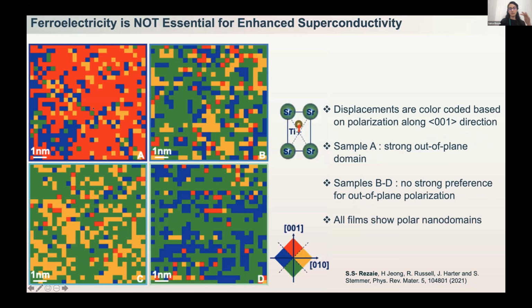Okay, these are the 4 films that we have looked at here. Film A, which I showed you earlier, had that strong transition to the ferroelectric state, and you can see that domains are forming in this structure. These domains are correlated, and they are mostly directional along the 001 direction. But for films B, C, and D, which are not transitioning to that global ferroelectric state, we still see correlated displacements happening in the structure.